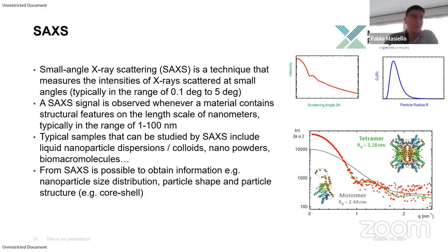Now we move away from the crystalline realm, and we can start looking at small angle X-ray scattering. This is a technique that measures the intensity of X-rays scattered at small angles. Typically, the range that is used is from 0.1 to 5 degrees. So there is a SAXS signal, like we see, for example, here, coming from one of our equipment. It is observed whenever there are structural features on the length scale of nanometers.